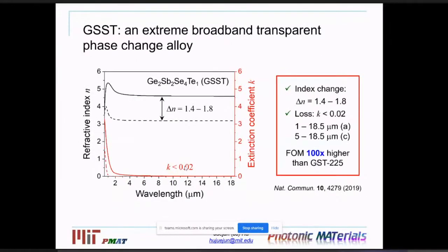Now, my group pioneered the first phase change material that exhibits broadband optical transparency across both amorphous and crystalline states. In the optical constants we measured, on the left-hand side figure, you see that it exhibits a very large optical property change from amorphous to the crystalline state, with an index change of about 1.5, which is huge. But at the same time, the material exhibits optical transparency across pretty much the entire mid-infrared to long-wave infrared wavelength range. This broadband transparency allows us to create a diverse range of optical devices that can capitalize on the bi-state transparency.